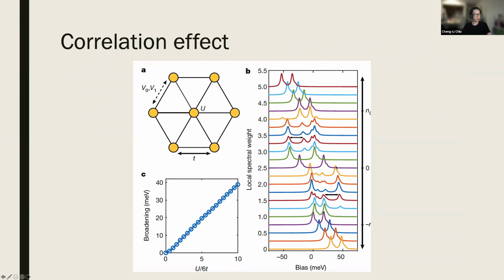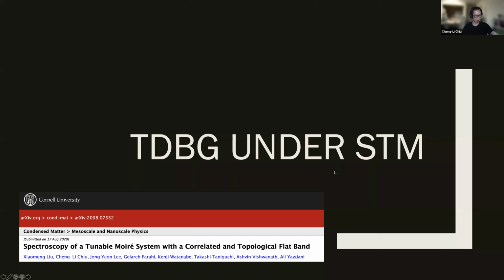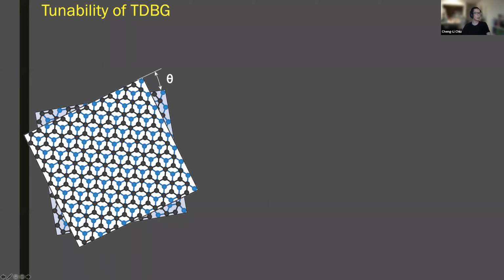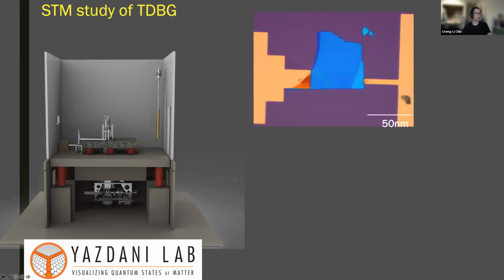So yeah, later I was planning to introduce another 2D material that I was involved in last year, twisted double bilayer graphene, but I guess I don't have too much time. But the gist is that it's very similar, but instead it's stacking two Bernal stacked bilayer graphenes. Bernal stacking is the natural configuration of graphene. So basically, when you exfoliate graphene, you get monolayer, you get bilayer, you get trilayer. And this is a bilayer graphene. And if you stack them, you also have some strong correlation effect.